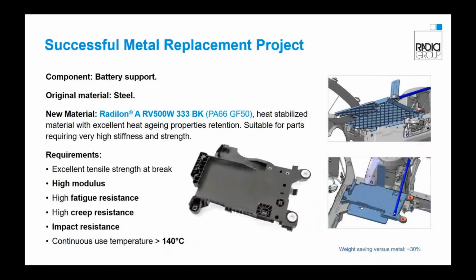For another automotive customer, we were involved in a metal replacement project of a battery support, which was previously made in steel. The material proposed for this application was a polyamide 6.6 with 50% of glass fiber. This grade has a superior thermal stabilization in order to meet the continuous temperature exposure of the part. And this grade shows very high mechanical properties. The requirements for this part were high stiffness and high strength, along with high creep and fatigue resistance.